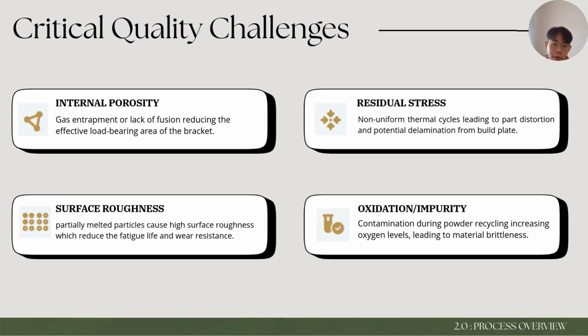Then is the surface roughness. This will happen because some melted particles during the melting process will stick on the surface of the product. This roughness will significantly reduce the fatigue life and also the wear resistance of our product. Then next is the oxidation of the titanium. As we know, titanium is highly sensitive, so oxygen contamination will make the metal become brittle and also unsafe when the metal oxidizes. Yeah, that's all.